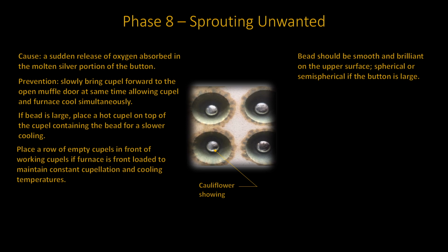Your beads should be smooth and brilliant on the upper surface. They should be somewhat spherical if your beads are small. However, they should be semi-spherical if your buttons are larger. The bottom of your button should have a rough texture and slightly adhere to the cupel. This is the result of the porosity of the cupel.